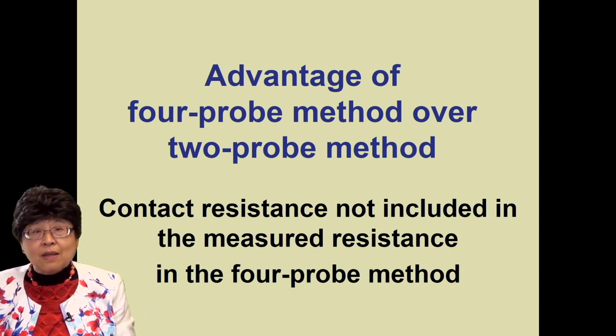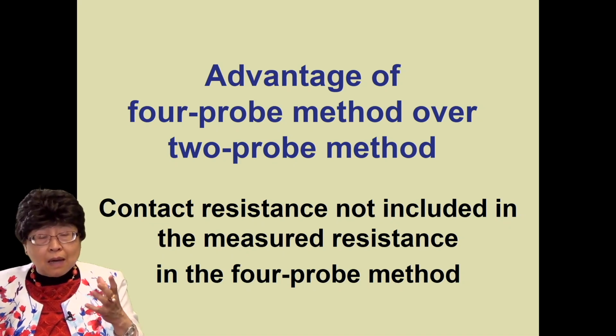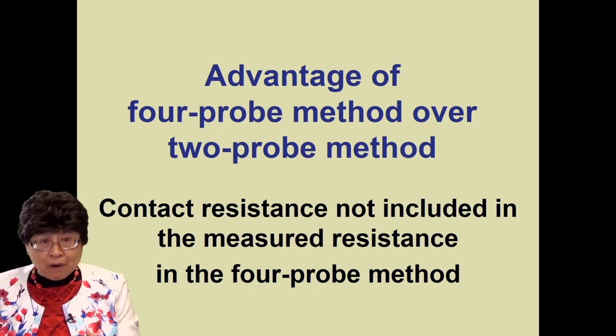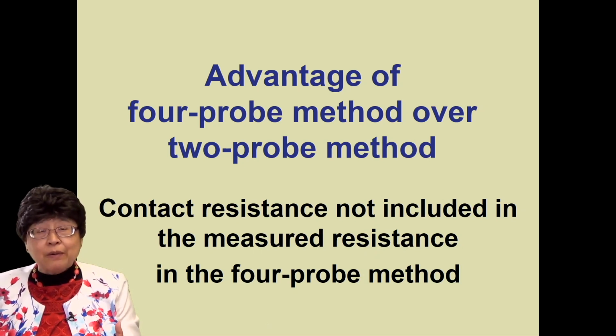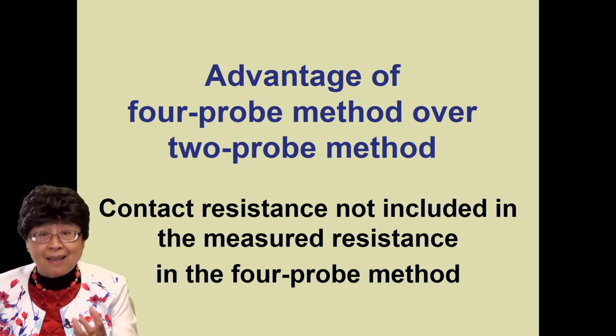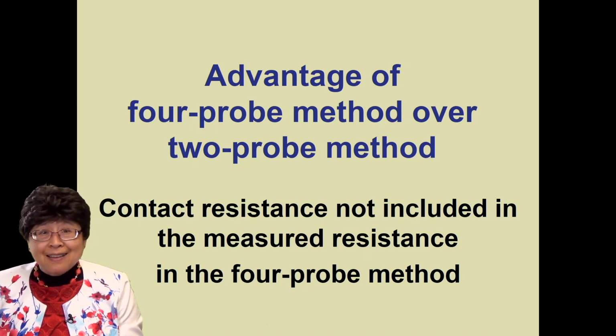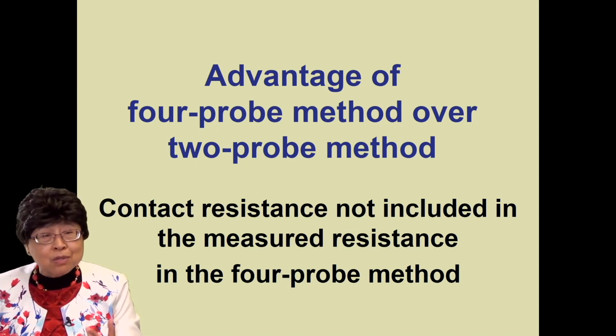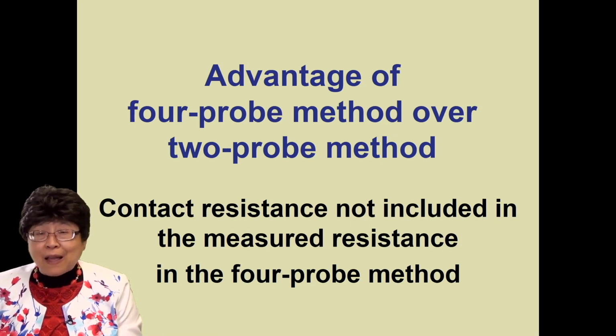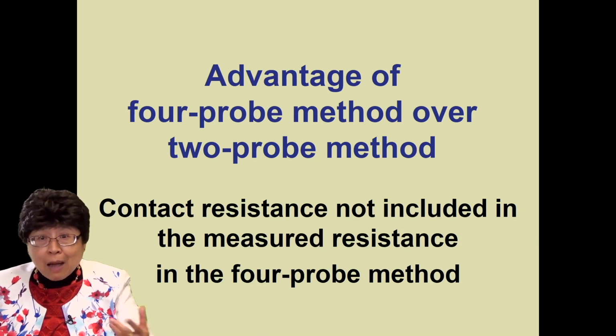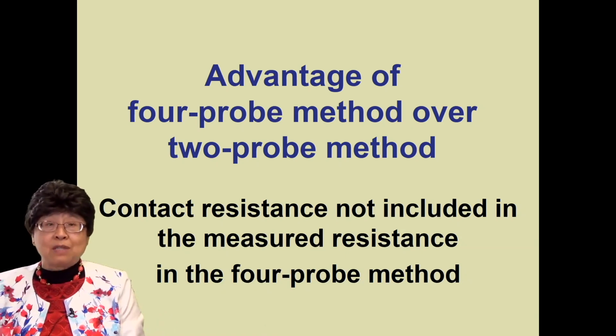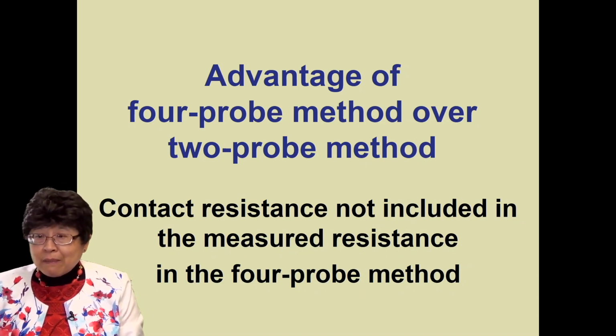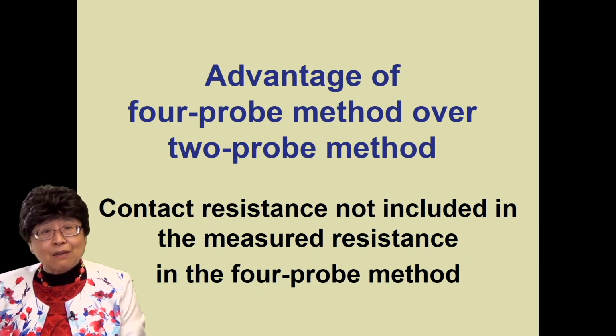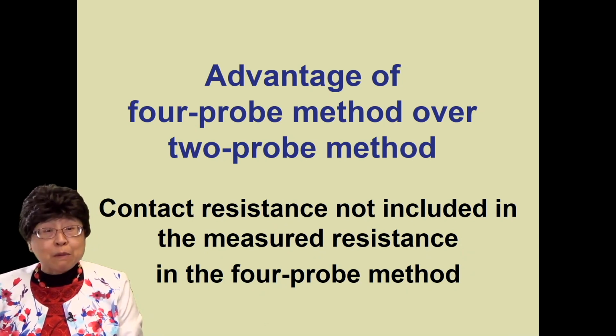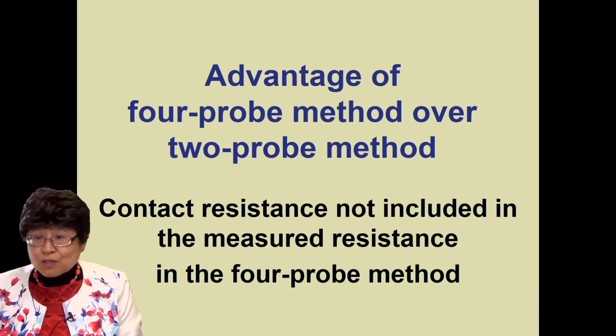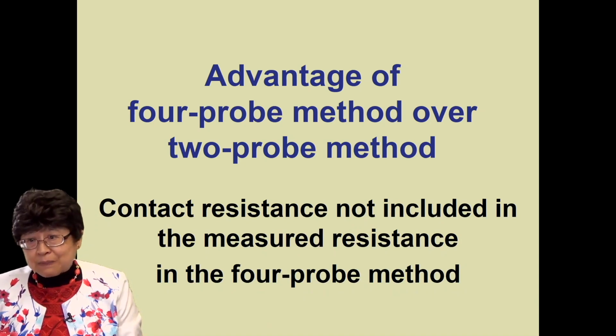Now, in the case that one is measuring the resistance while the stress or strain is changing, there's a further problem, because as the material experiences the stress or strain, the quality of the electrical contact might change. And so the contact resistance might change as you impose the stress or strain. That effect can even possibly dominate the change of the specimen resistance with the stress or strain. So it's very important to take away the contact resistance from the measured resistance. A lot of papers have been published using the 2-probe method, and unfortunately, most of them have incorrect results.